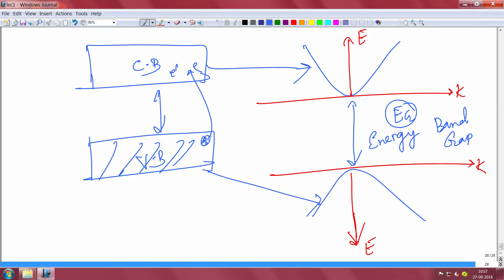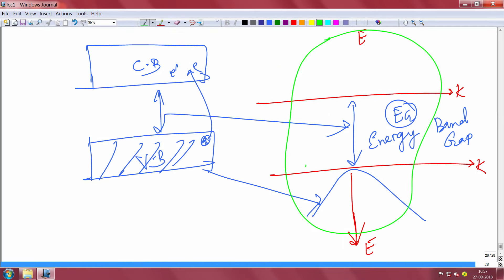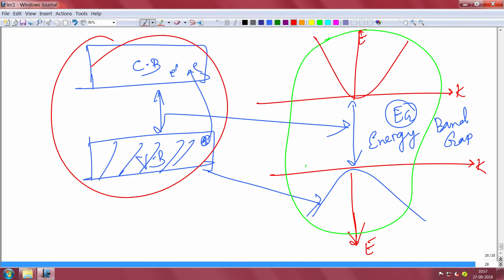So holes are in the valence band and electrons are in the conduction band. The E-k diagram for both electrons and holes together shows this gap between them — that is the energy band gap E_g. The valence band corresponds to holes and the conduction band to electrons. This full E-k representation is called the band structure, while the real-space version is called the band diagram — there is a one-to-one correspondence between them.